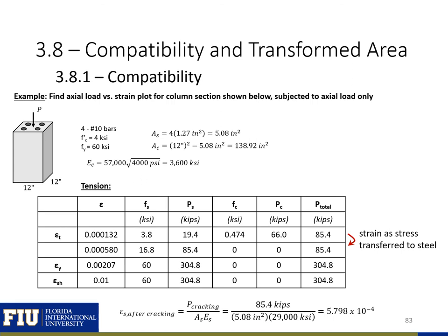This means that all of the force in the column will transfer from the concrete and steel together to just the steel. This will cause the steel to experience additional deformation or strain as it takes the force from the column. We can determine the strain in the steel immediately after cracking by taking the cracking load divided by the steel area to give the stress in the steel, and then divide by the modulus of elasticity for the steel to give us the strain. In this case, the column will increase in strain to 0.00058 as the stress is transferred into the steel. Two additional points were found in tension, the yield strain and the strain at the end of the yield plateau.